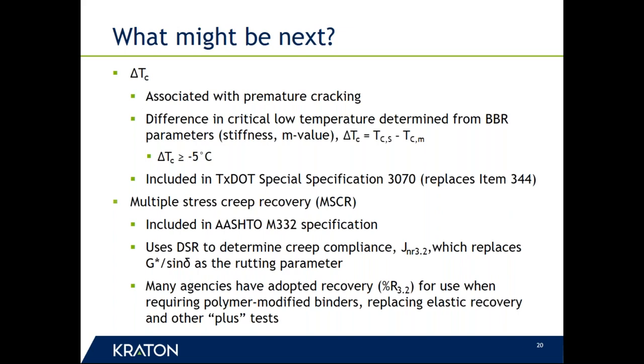The multiple stress creep recovery test, or MSCR, is probably the basis of the AASHTO M332 specification I mentioned before. It uses a dynamic shear rheometer, so there's no change in equipment, but it changes the procedure slightly in order to determine some different factors that are better predictors with respect to rutting in particular.